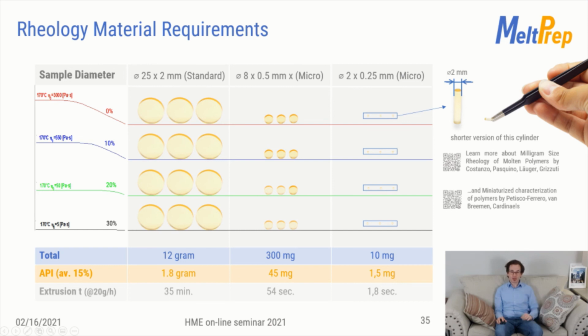Will it save us material? We have depicted the requirements here. Standard rheology tests are done 3 times for each API concentration. 12 samples weigh around 12 grams with 1.8 grams of API. To reduce the amount of material, you can do micro-rheology. 12 samples with 8 mm diameter require 300 mg of material and only 45 mg of API.